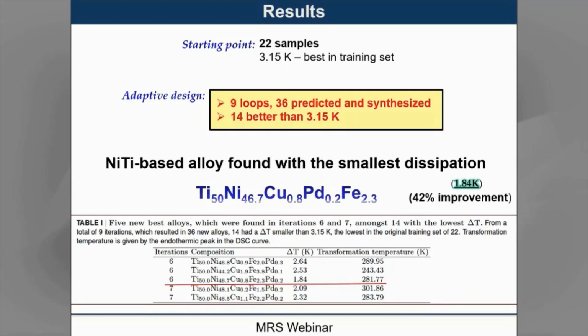But intriguingly, one of the interesting things that we found in this exercise was that this new alloy was discovered not at the first iterative step, right? As noted in this table below, this new alloy actually came into existence during only the 6th iteration of our adaptive design exercise. And we believe that this has to deal with the way the optimal learning method had allowed us to survey the search space starting from the small training data. And this was an illustrative exercise for us to learn about how this process in fact works and how this can indeed lead to new materials with properties better than what we actually started. Right? This was one of the important case studies where we really demonstrated the potential of this approach for accelerated design and discovery of new materials.